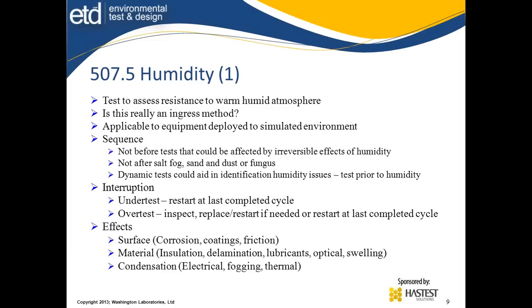The effects are surface effects: corrosion, the coatings, the friction, you remove coatings, and so on. The material: insulation reduction, delamination, removal of lubricants. You end up with oils and films that prevent friction issues, so you end up with the lubricant missing. Optical things, where the moisture creeps onto the lenses and so on, so you cannot get the visual things.